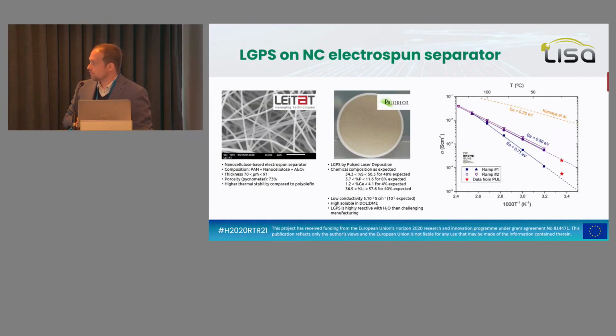Here you have LGPS on top of a specific separator that we developed by electrospinning. Why we use nanocellulose in this case is because it has unusual thermal properties with respect to polyethylene, which is the baseline for separators for lithium-ion batteries, polyethylene, polypropylene. Nanocellulose gives you a much higher temperature for the processing, so this is also an important parameter when you want to make physical deposition or this kind of thing.